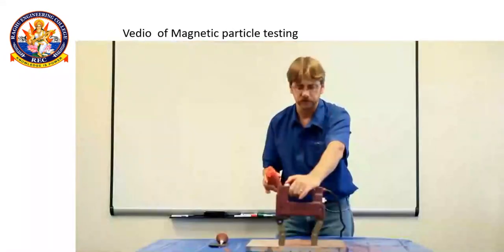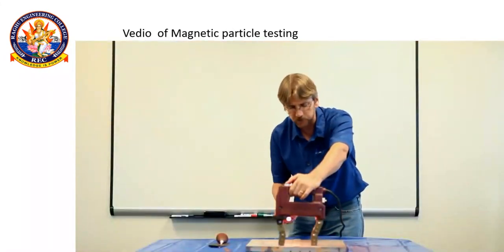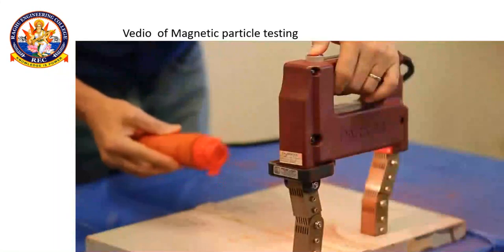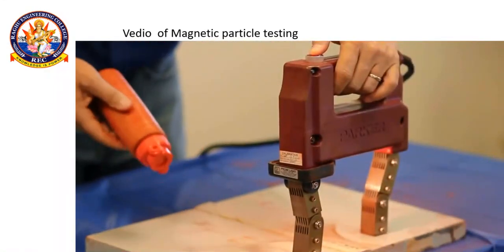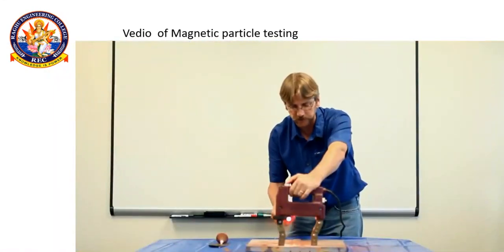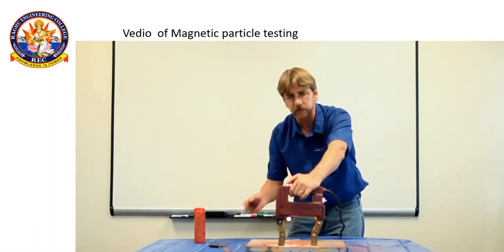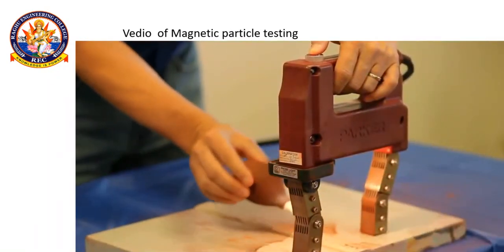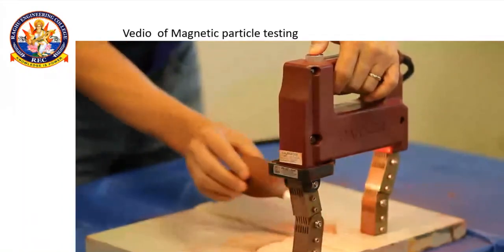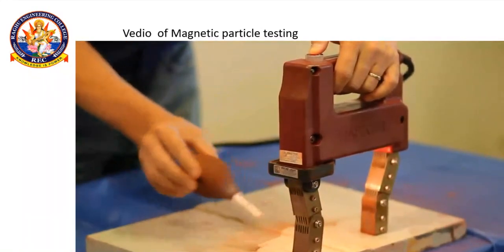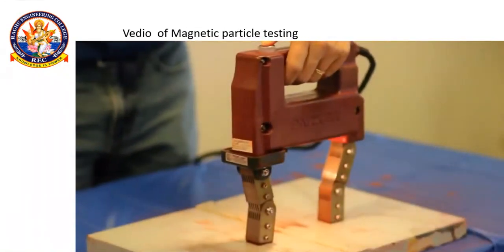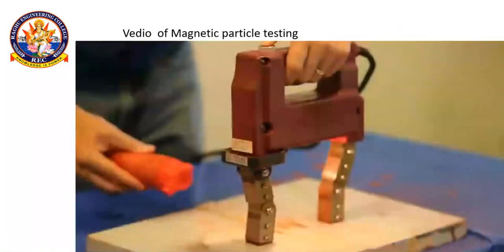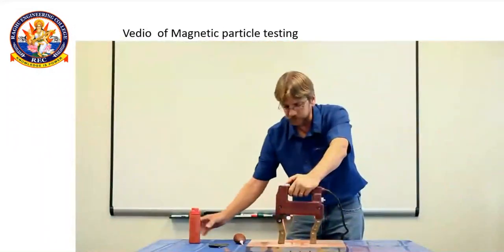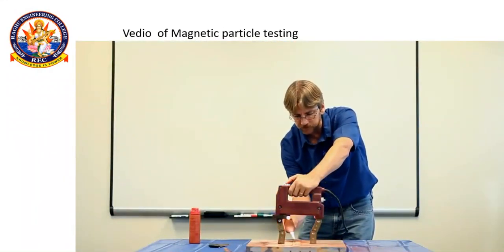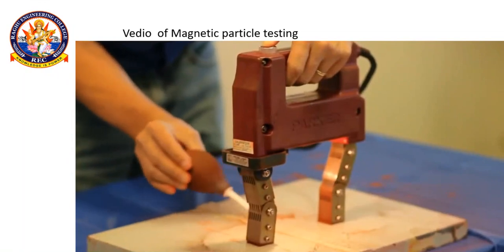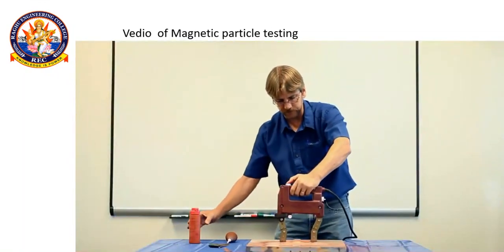It is a welded plate. Two plates are welded to each other, and he placed the magnet on opposite sides of the weld, and he is spraying some iron powder, ferrous powder, in between the poles. Whatever excess powder is there, he is blowing out with the blower. Because he switched on that portable magnet equipment, the two ends of these poles are converted, one into a north pole and the other into a south pole.